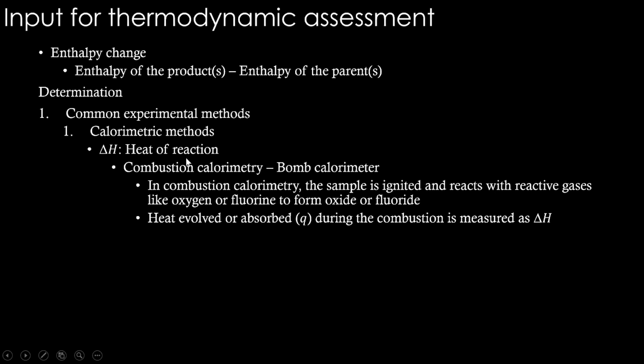The heat of reaction for certain reactions such as combustion can be measured in combustion calorimetry. Things like a bomb calorimeter can be used for this purpose. In combustion calorimetry, the sample is ignited and it reacts with reactive gases such as oxygen or fluorine to form an oxide or fluoride. So this will be a highly exothermic process, and the heat evolved or absorbed during the combustion is measured as delta H.